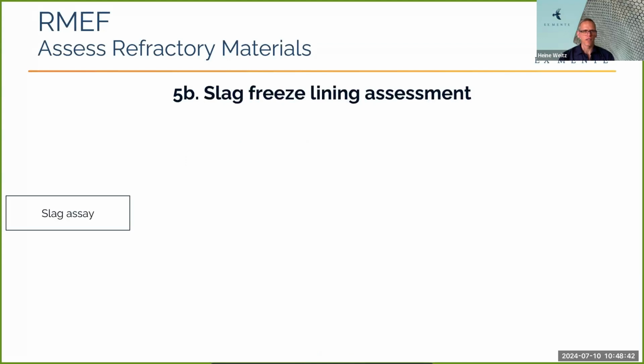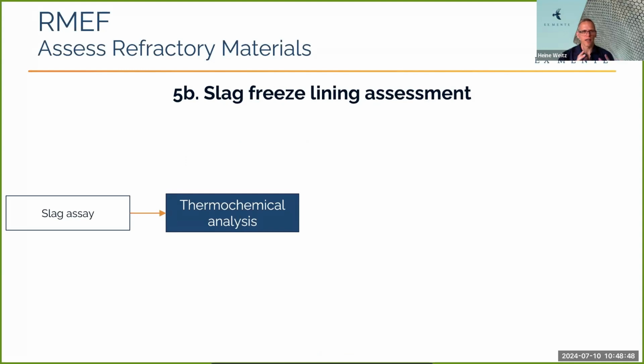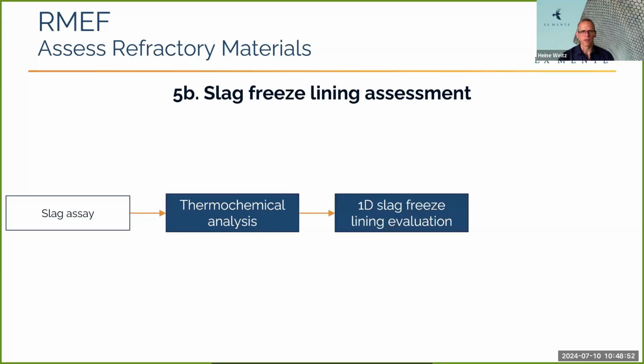Okay, then for slag freeze lining assessment, we can take a slag assay, perform a thermochemical analysis on it to understand how the slag changes as a function of temperature. And then with a simple 1D multiphysics model, we can estimate the likelihood of a slag freeze lining forming, and then understand what the stresses and strains are in the refractory material.